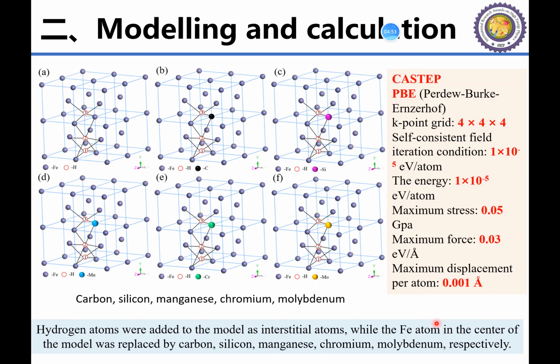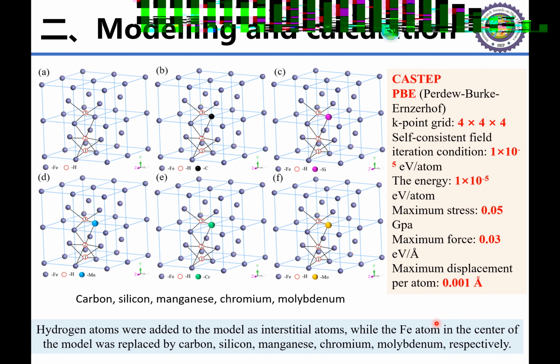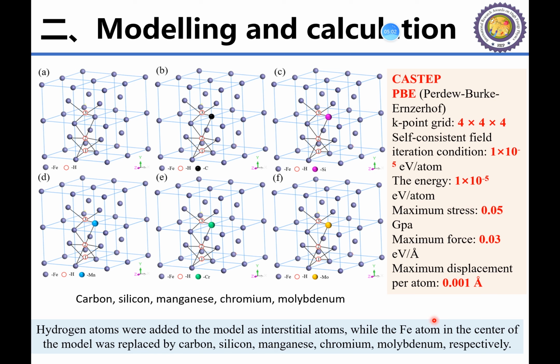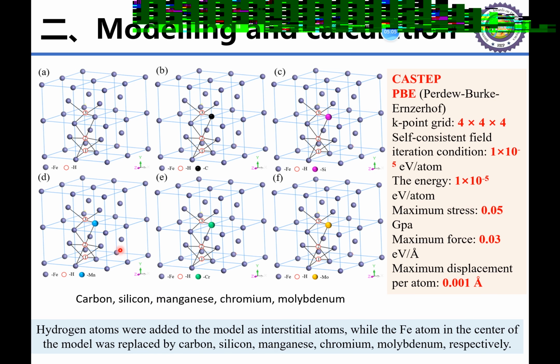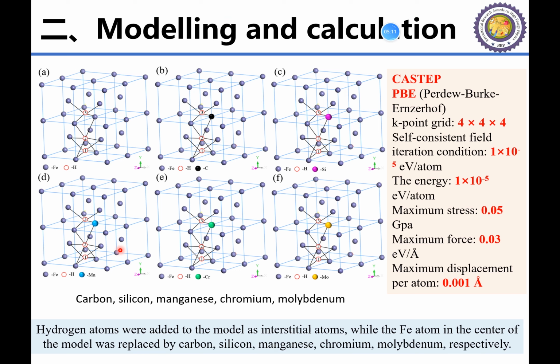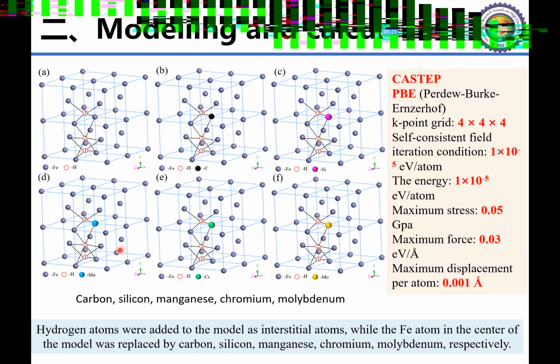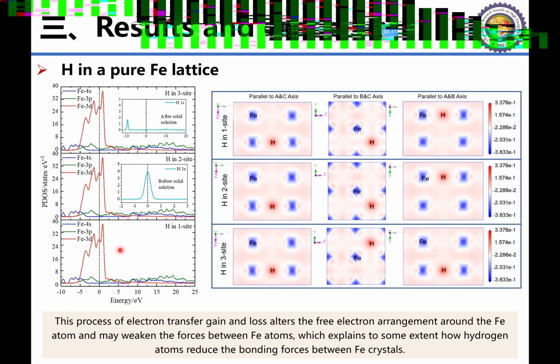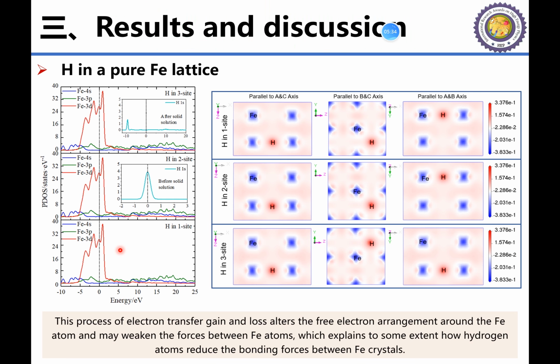And the second part is modeling and calculation. Hydrogen atoms were added to the models at the interstitial sites, while the iron atom in the center of the model was replaced by carbon, silicon, manganese, chromium, molybdenum, respectively, and the hydrogen in a pure iron lattice.